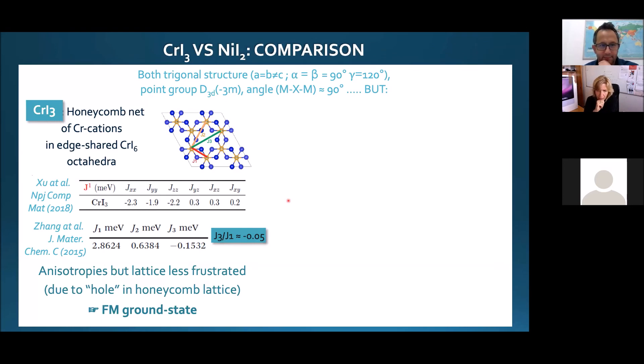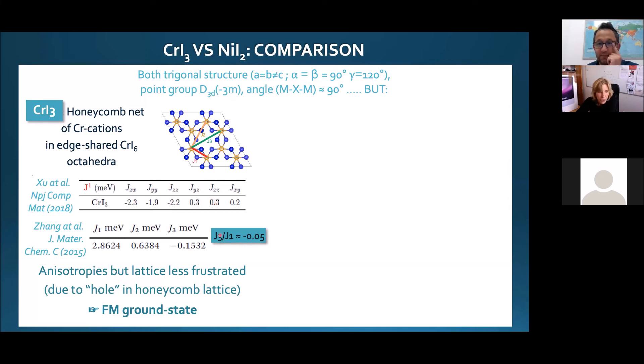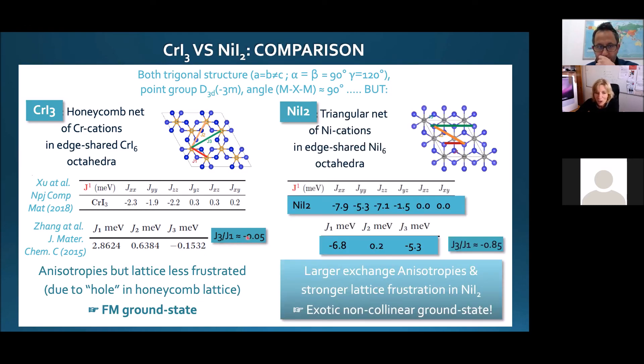Can this happen in chromium triiodide—the paradigmatic 2D magnet? People have calculated the exchange matrix for CrI₃ and shown there is some anisotropic exchange. However, the J3/J1 frustration is not there, and we believe it's absent because CrI₃ has a honeycomb lattice with a hole, so J3 lacks the path to mediate the interaction and is very small. As I said, without J3/J1 frustration, you can never stabilize an anti-skyrmion pattern. Chromium triiodide is indeed well known to be ferromagnetic.